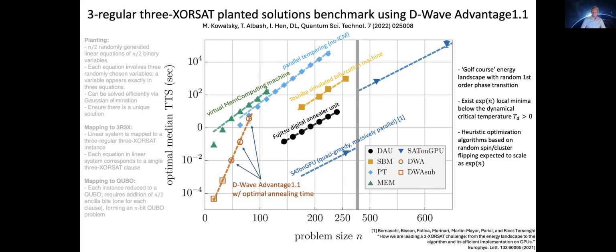So we did a pretty broad study of scaling and benchmarking in this case. And so here is the time to solution as a function of problem size for D-Wave versus a number of classical methods. So the first thing you notice immediately is that this now is with the D-Wave advantage, with the circles denoting cases where we were able to certify an optimal anneal time once more. So you can trust the scaling here. The D-Wave slope is significantly worse, unfortunately. The winner in this competition was the SAT on GPU algorithm due to the Parisi group, which beat out the Fujitsu digital annealer and the Toshiba simulated bifurcation machine and the virtual memcomputing machine and parallel tempering.